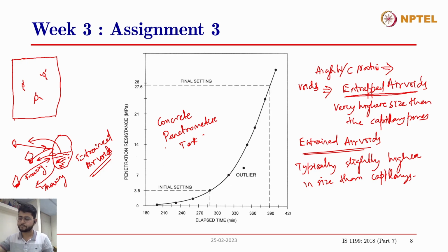And you can see that the code assumes that when the concrete gains a penetration resistance of around 3.5 megapascal, that is regarded as the initial setting period of the concrete. The concrete is believed to have set initially, and it has gained enough green strength so that it will not have any kind of deformation or cracking due to, let's say, placement or some accidental situation.